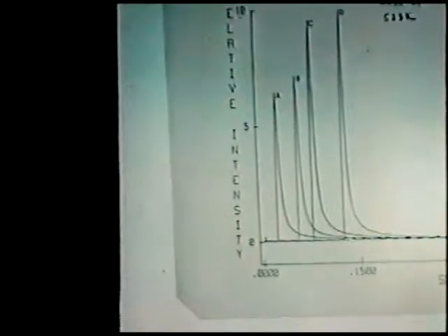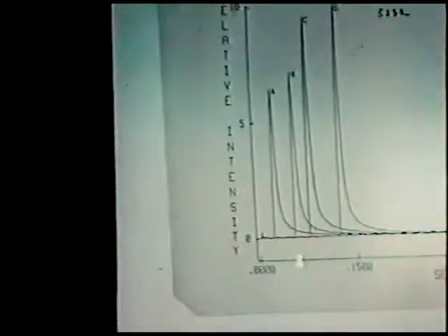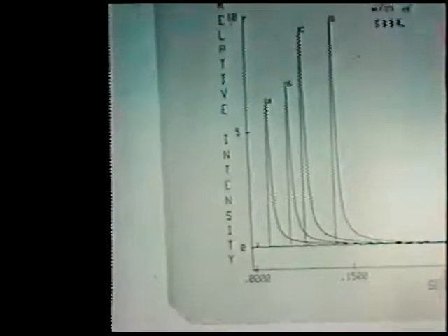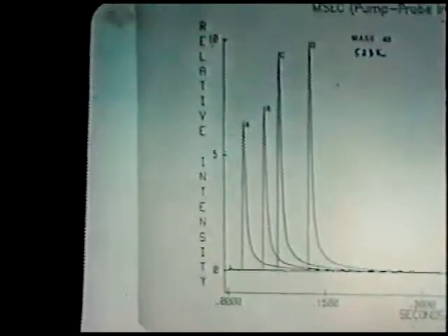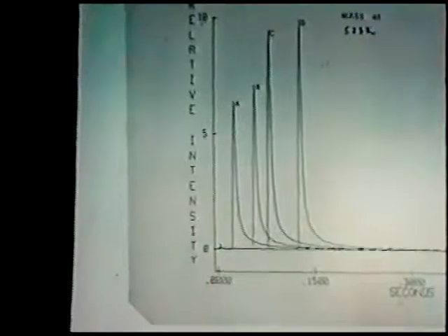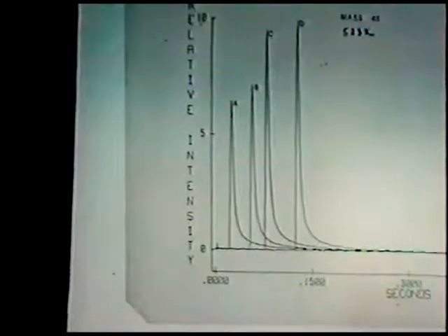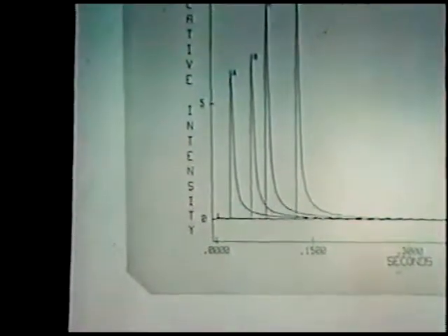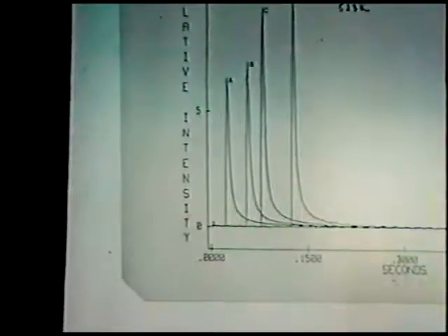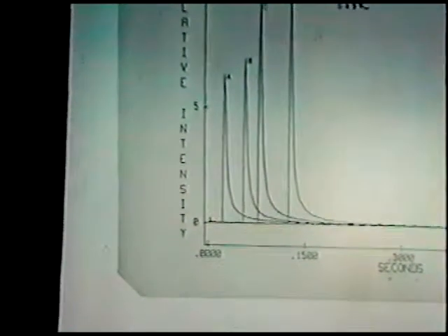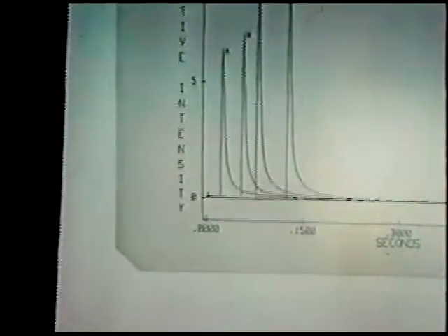And this process has a time which is about the order of a tenth of a second. Now, we don't understand the details of this. John Gleaves is currently investigating this further. It may have to do with reorganization of oxygen in the surface and subsurface layers. It's known that subsurface oxygen is important for the formation of ethylene oxide. And since we're stripping off the oxygen in the pulses as we go through, at very short time intervals, it may be necessary for there to be a rearrangement, if you like, transfer of oxygen into the subsurface layer in order to produce ethylene oxide with high efficiency.